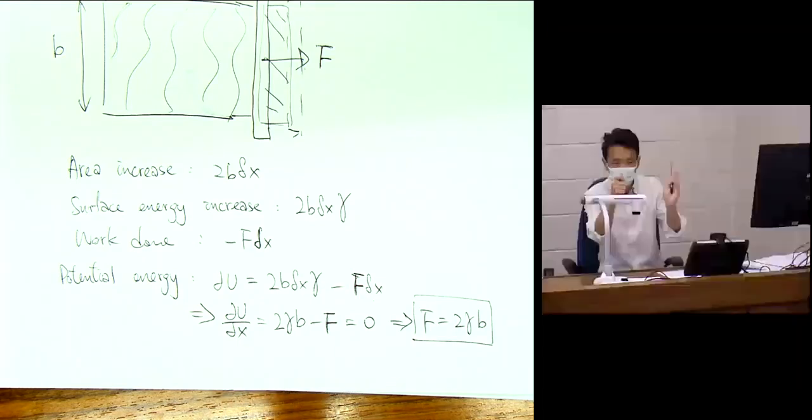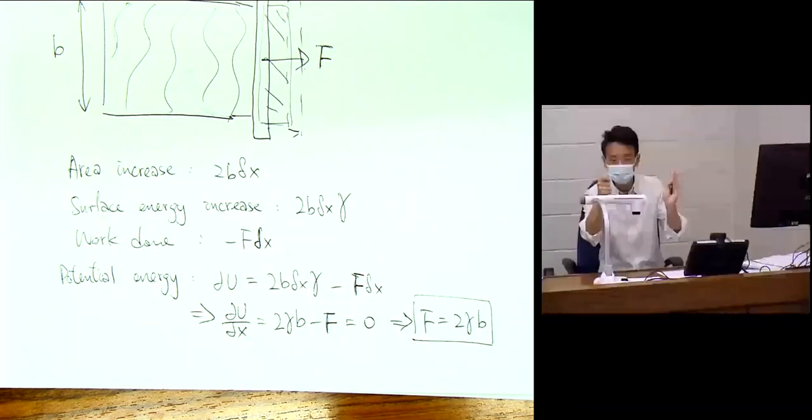What you're going to do is actually break the film. Yeah, because the surface energy is this much, and when you apply more than that, right? So you have to always be at the equilibrium. You maintain the force at the equilibrium force while quasi-statically stretching it without increasing the force. Then you can stretch it out, but you have to be very steady, because a slight increase in the force is going to break the film, right? So that's an excellent